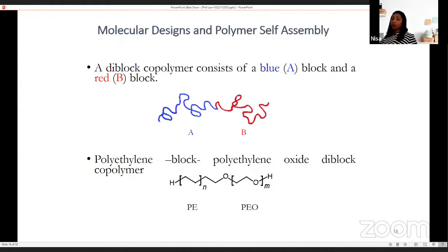But these block polymers can undergo a phase separation process, and that's the way they make structures at nano level. Here is a diblock polymer called polyethylene block polyethylene oxide. This is an amphiphilic block polymer where the polyethylene block is hydrophobic in nature. When such a polymer dissolves in water, the molecules self-organize in such a way that all the hydrophobic parts form the core and the hydrophilic part forms the shell. That's the way they form sphere-like particles at very nano level, and they are called micelles.